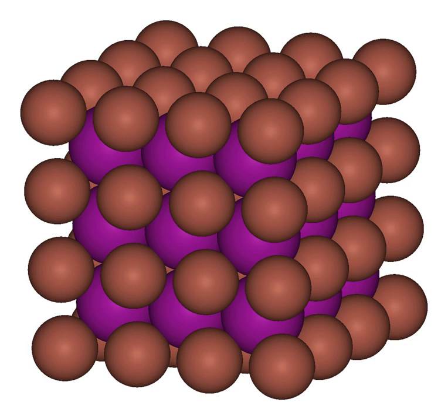At 62 degrees Celsius it transforms to a tetragonal structure. This structure is unchanged up to a pressure of 40 gigapascals. The room temperature structure has been explained in terms of interaction between Tl 6s and the F 2p states producing strongly antibonding Tl-F states. The structure distorts to minimize these unfavorable covalent interactions.